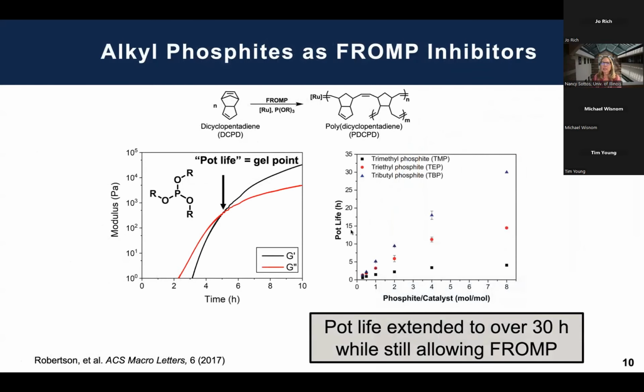As I mentioned, the key to this all, I'm going to go over the chemistry very quickly, is this inhibitor, because basically you mix all these components together to formulate it. It's an active system that could react, but you have an inhibitor that gives you some time, some pot life in order to infuse it into a composite or print it. And so we've worked a lot with these phosphite inhibitors that can give us, with the right formulation, up to 30 hours of working time.